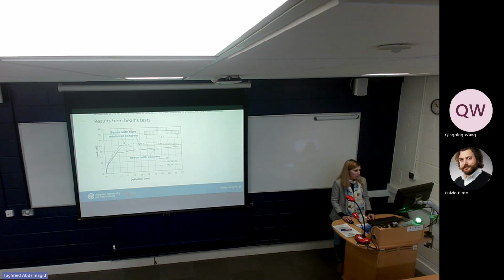And what did we discover? First of all, we were very surprised. In our tests, I'm always saying that in our tests, we achieved an increase in load bearing capacity of about 20%. So this is a huge difference. When we add the fibers, we have an increase of load-bearing capacity. We didn't expect that. We expected the biggest influence on resistance to cracking, not on load-bearing capacity.